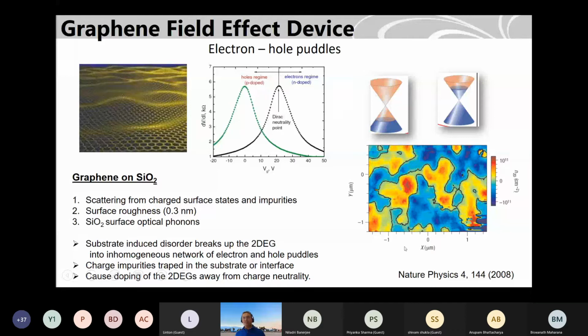Especially within a few micrometers, you see lots of electron and hole puddles. So it's called electron hole puddles. And when you do such an experiment, you see that graphene is heavily doped. The Dirac point is not at 0. And when you sweep back, you also see hysteresis. So you never know where you are in the system when you are measuring.